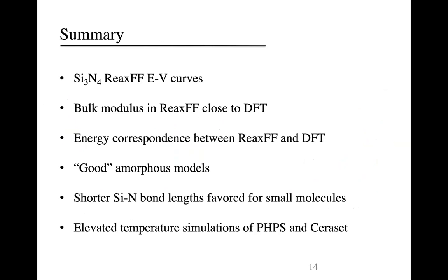In summary, we parameterized a new set of ReaxFF parameters. We evaluated silicon nitride parameters by calculating energy volume curves for silicon nitride and found that ReaxFF generally agrees with DFT, though encounters some issues with low and high volume structures. Using the energy volume curves, we calculated that the ReaxFF bulk modulus for alpha silicon nitride was close to the DFT value. Additionally, we found that ReaxFF energy differences do correspond to DFT energy differences, though for these parameters, ReaxFF energy differences are only about half the value of DFT energy differences.